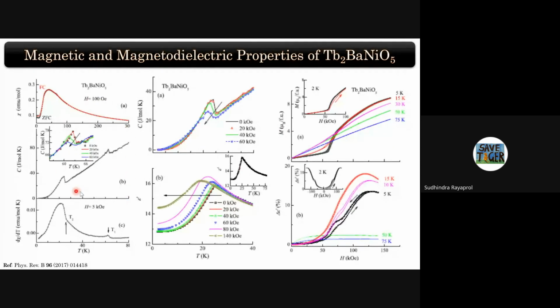What it shows is that in heat capacity or magnetization, you find small humps at 63 and 25 Kelvin, which are confirmed to show a change in magnetic order. From T1 to T2 it is an antiferromagnetic order, and below T2 is another antiferromagnetic order. So there's an order to order transition. But if you look at heat capacity, you don't see any anomaly around 63 K. You see only the anomaly, or field dependence anomaly, at 25 Kelvin. If you look at the dielectric data as a function of field, you will find that at 25 K only you see these anomalies.